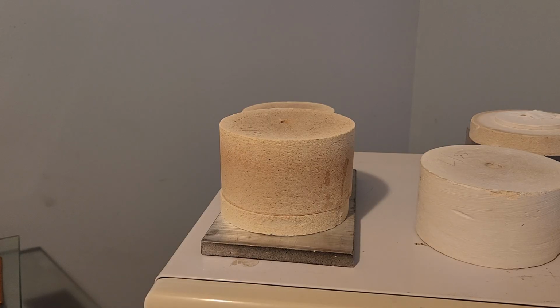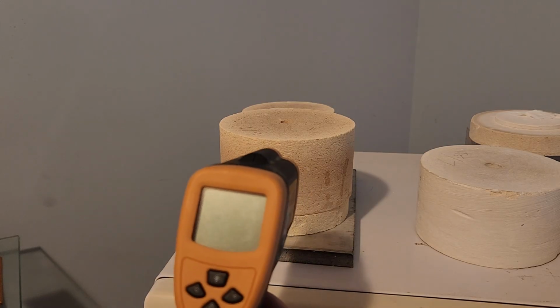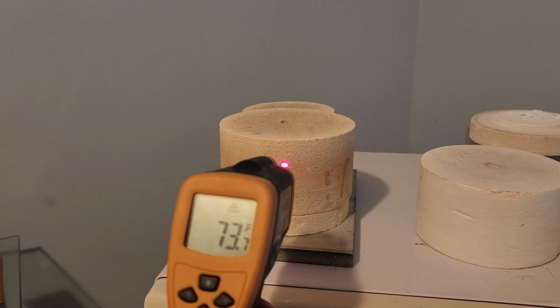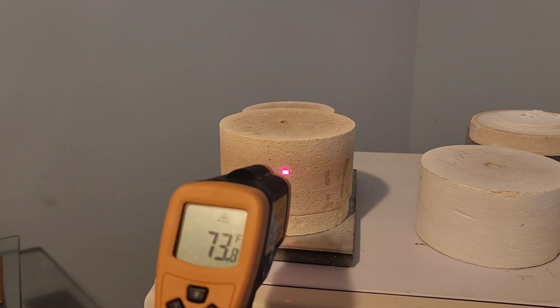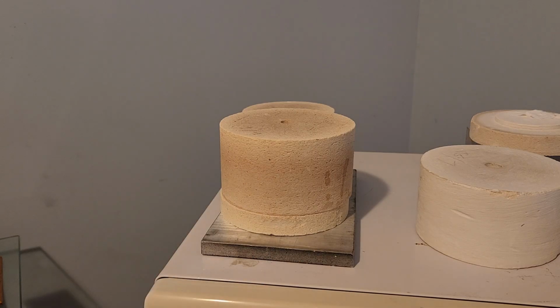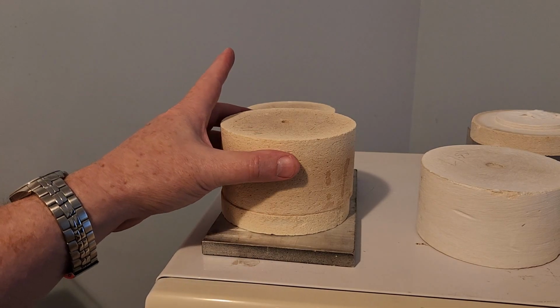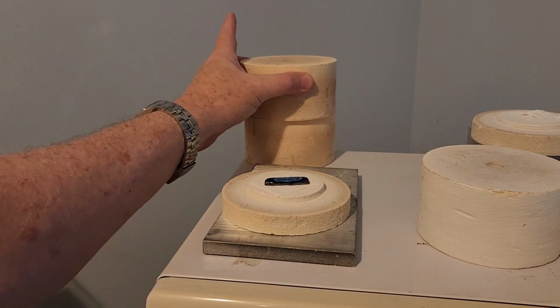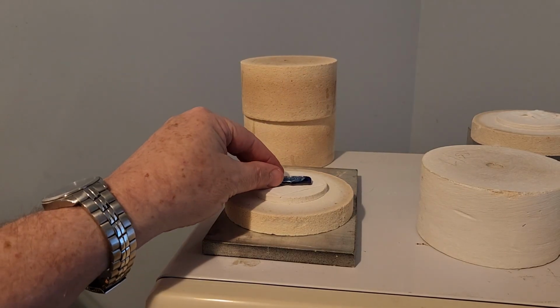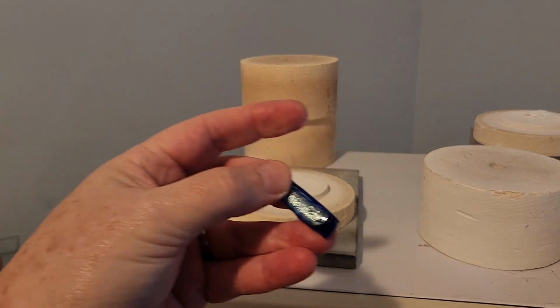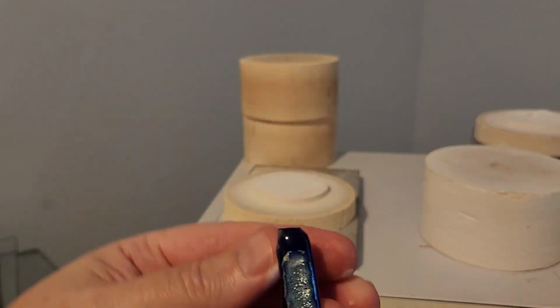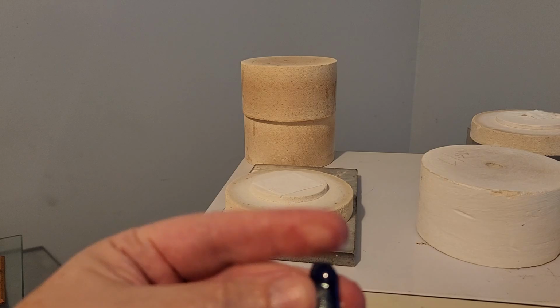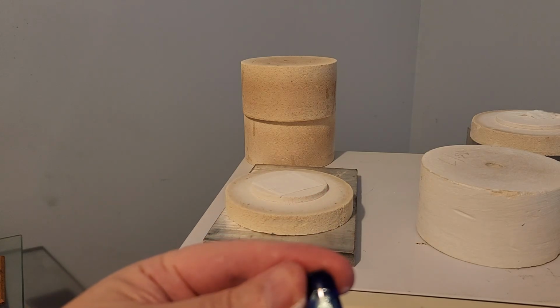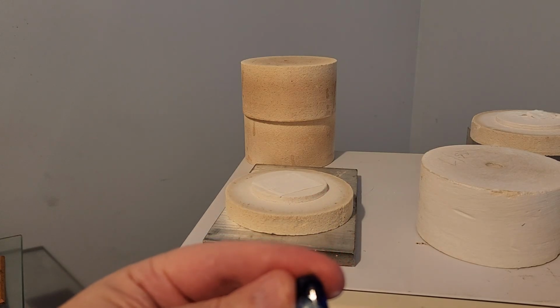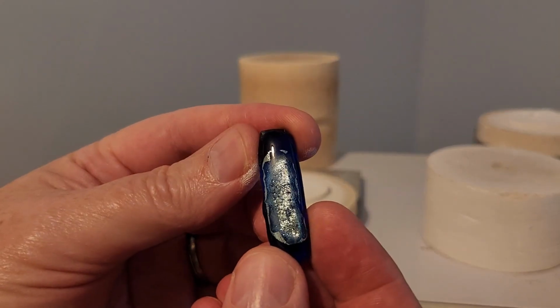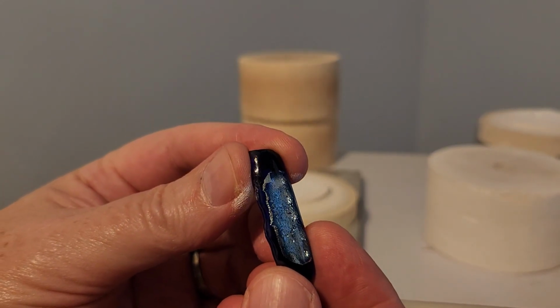So the kiln is cooled down. I can see that it's about 73 degrees, the same temperature as the house. So I know what's in it is cool. Go ahead and open it up. That looks pretty good. So it came out pretty nice. The back is really smooth because of the prep that we did on the kiln and using the kiln paper. And it looks pretty nice.